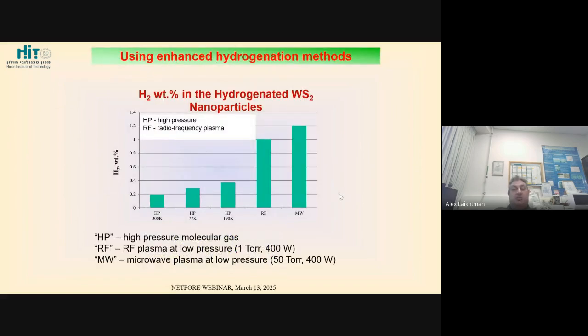For this type of process, we used several kinds of hydrogenation methods. The easiest and most popular is just high pressure hydrogen, so just exposing to hydrogen at high pressure. It could be done at room or high temperature or low temperature. And here you can see the weight percent of hydrogen. As you can see, the weight percent of hydrogen for high pressure molecular hydrogen is very small. Though I have to tell you that because the molecular weight of hydrogen is just 2, and the molecular weight of WS2 is 247, this very small weight percent is still a very high atomic percent. But anyway, it's not enough. By using intermediate low temperatures, we improved the situation.